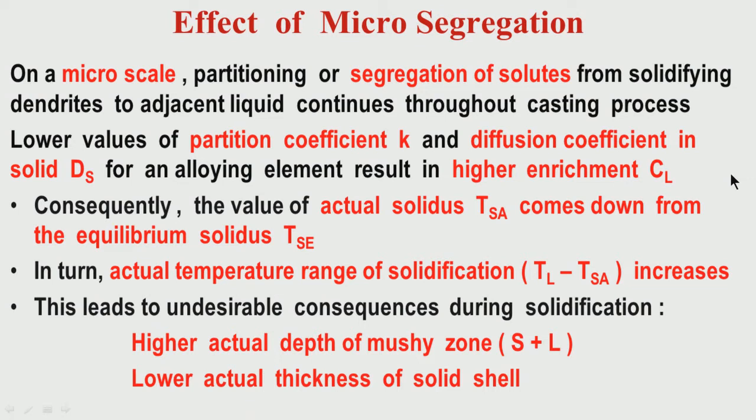So, the final liquid which is solidifying has a much lower temperature. So, that particular solid which is solidifying is more rich in the alloying elements. So, the last area which is solidifying, which is heavily segregated, that means the concentration of all alloying elements in that area is relatively more compared to an area which is solidified during the early stage of solidification.